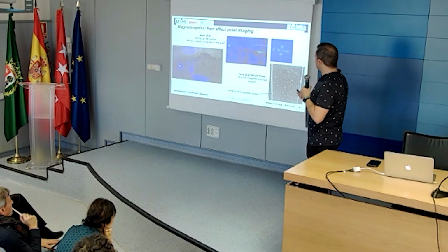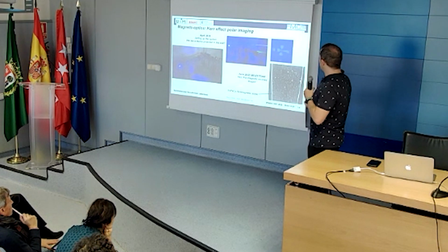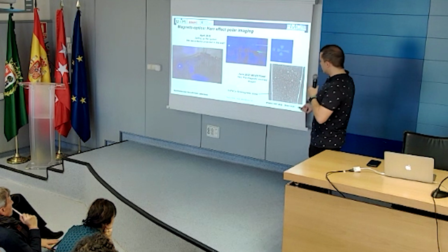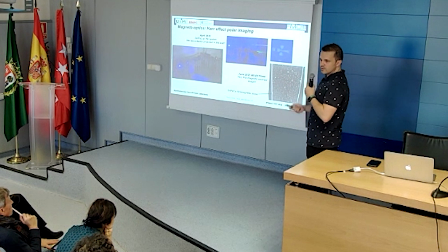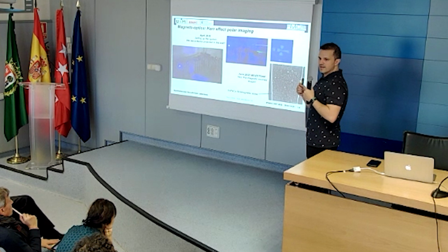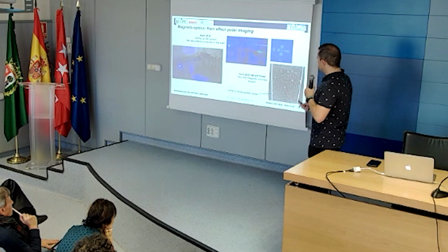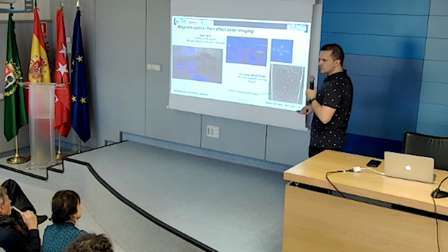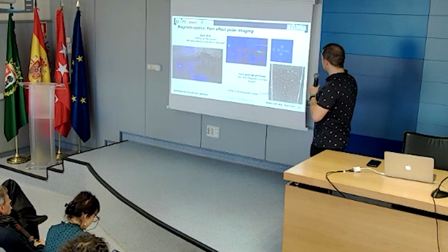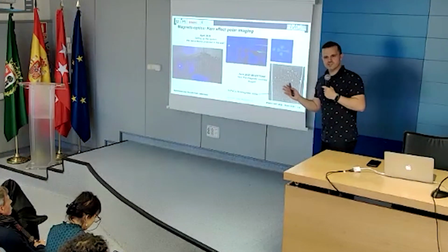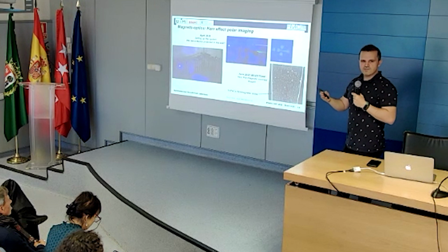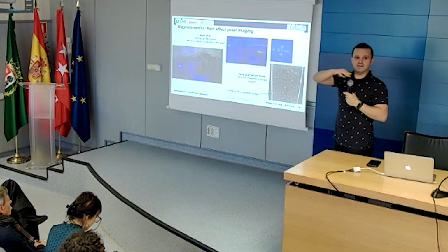Then later, with a little bit more work, we could get these magnetic contrast images. Here you can see up and down domains, and that's with the ferrimagnetic layer. Ferrimagnets have much less magnetic moment than ferromagnets. So that was already a success, that we could see a ferrimagnet that was a few nanometers thick. Now we still have a lot to optimize.